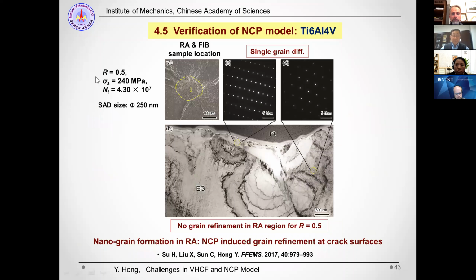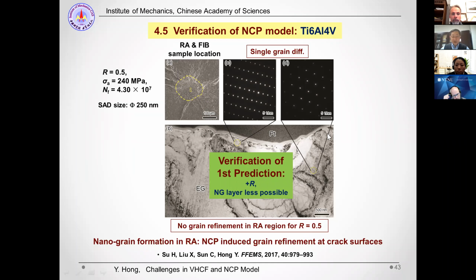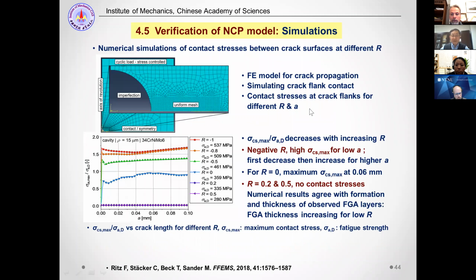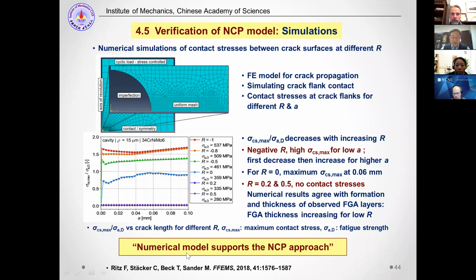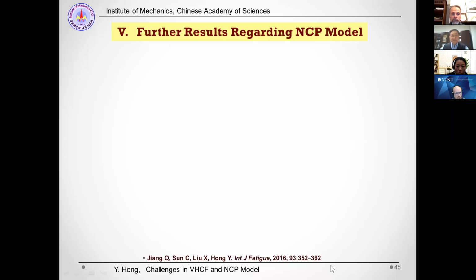Also, we use titanium alloys. The loading is under 0.5 stress ratio, and we see no microstructure refinement happens in this case. So this is also a verification of the first prediction. And also there's a numerical simulation by German researchers. Their result shows that under the negative stress ratio, there's a large contact stress. But for positive stress ratio, the contact stress is almost zero. So the numerical simulation supports the NCP model. Okay, now the further results regarding the NCP model.